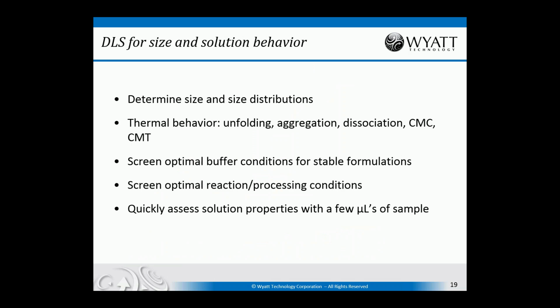So to summarize the use of the dynamic light scattering tool, or light scattering tool number one, it helps us characterize size and solution behavior. It will give us both the size and rough size distributions over a large range, from sub-nanometer up to microns. It will help us determine the thermal behavior, including unfolding, aggregation, dissociation, CMC, and CMT. It will help us automatically screen optimal buffer conditions for stable formulations, for optimizing our processing conditions or reaction conditions, and it will quickly assess these solution properties with just a few microliters of sample.